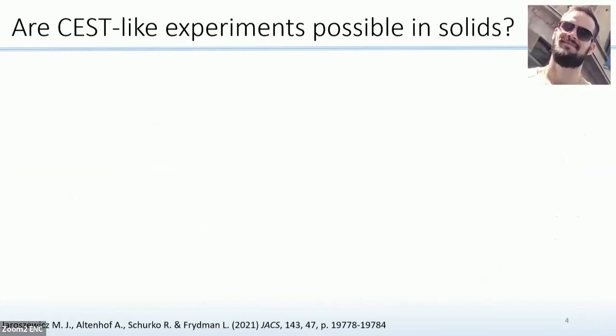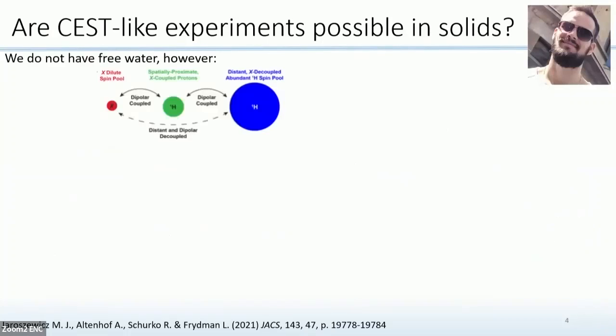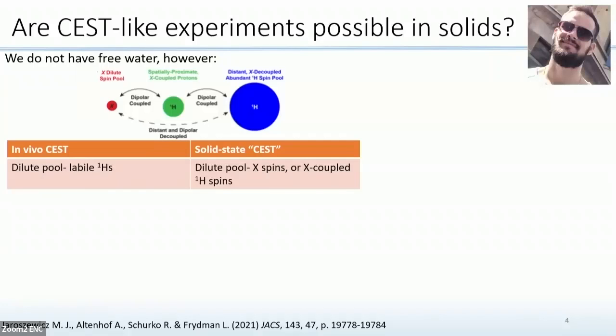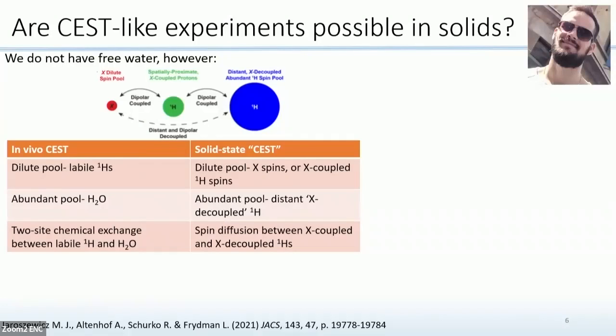So we were wondering if these types of CEST-like experiments would be possible in solids. And in solids, we don't typically have free water, but we did notice a few points of similarity to CEST experiments. One of them is that the dilute labile protons that are usually found in CEST can be analogous to dilute X spins that we have, or alternatively, the pool of protons that are coupled to these X nuclei. And then instead of the abundant pool as water, we would have abundant distant decoupled protons that are marked here in blue. And then also, instead of exchange, the analog would be spin diffusion between these two pools of protons.